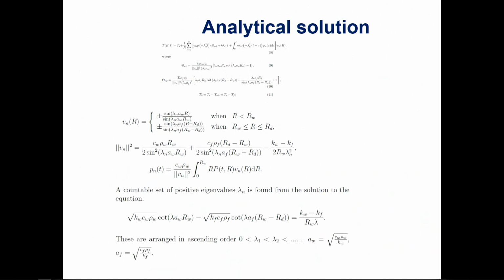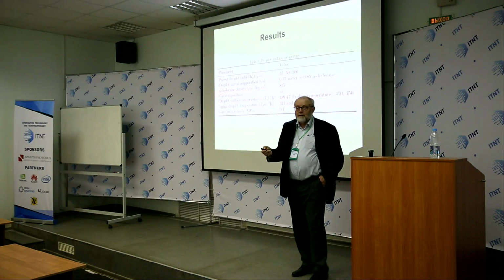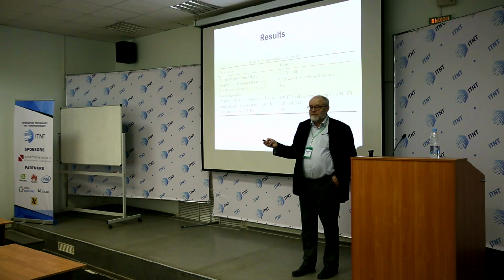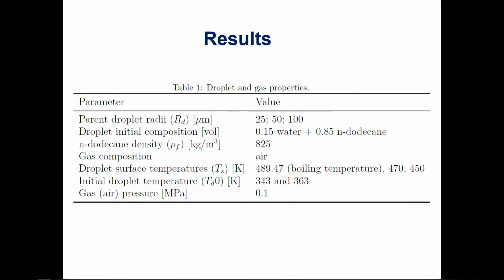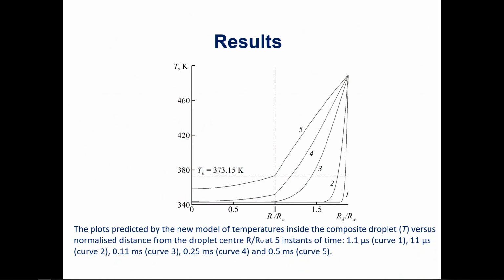And then, once we reached the solution, we applied it to a particular experiment, which was performed in a group at the University of Petronas in Malaysia. And these are input parameters for the droplets, which were supplied by my colleagues working at that university. And as a result, using this solution, we were able to describe the heating of the droplet with time.